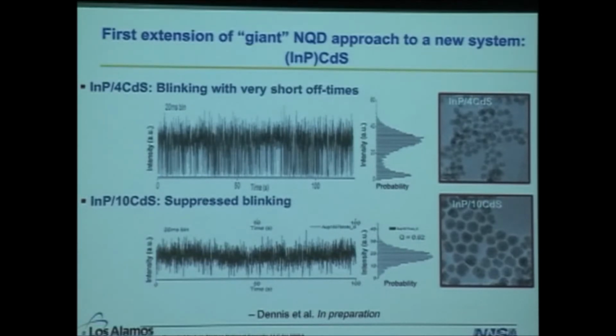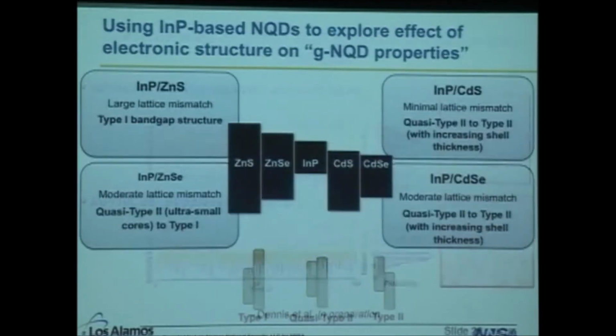And I know I harped on the 1 hour thing. Because these are actually emitting in the near infrared, this is hard work to get this data. What we're waiting for is to find our best sample, and then I'm going to make the poor postdoc take it out for an hour so we can look at photobleaching effects. But we can't do that as we go. But that's kind of exciting.